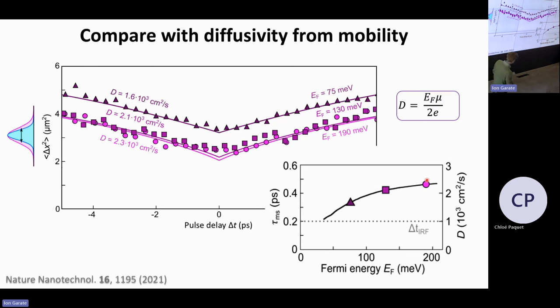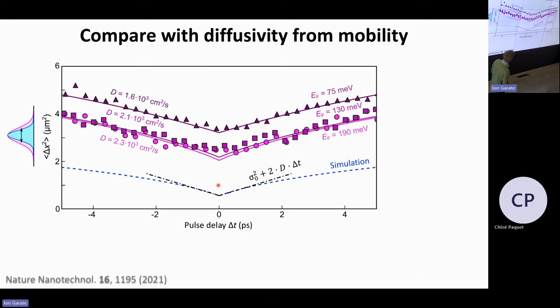But then we started looking a little bit better. We realized that there's something weird about these data, which is that there's this offset that's different between the high Fermi energy and the low Fermi energy. And in fact, from our spot sizes, we were expecting the data to start somewhere here, so much lower. So there seems to be something going on that changes this offset. So where's this offset coming from? Exactly, even from theory, we were expecting it to start even down here.